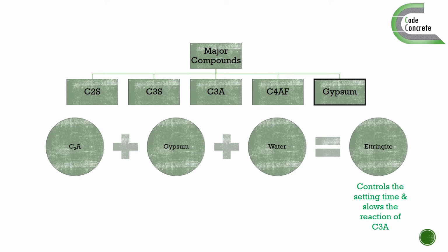The amount of gypsum used in cement is crucial during the hydration process. If tricalcium aluminate is depleted before gypsum, the excess gypsum that remains expands, causing cracks and reduced durability. Whereas, if gypsum is depleted before tricalcium aluminate, the surplus tricalcium aluminate will eventually react with the unstable ettringite to form monosulfate aluminate hydrate crystals, which negatively affects the durability of concrete subjected to sulfate attack.